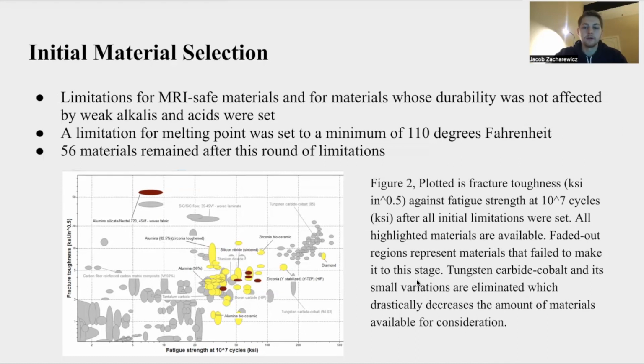And this is the fracture toughness versus fatigue strength graph after that. All of the gray is all of the materials that didn't make it. As we see, all the tungsten carbide cobalt has not been able to meet those limitations, which is one of the main reasons why only 56 materials remained out of this.